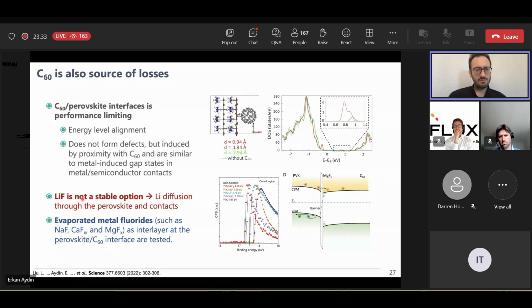in the past by lithium fluoride, but this is not a viable option for the long term because lithium fluoride is a bit tricky. Lithium is diffusing into the perovskite and other contacts, and in the end, we lose this layer, and plus it's also causing performance losses. So you can use any other metal fluoride as well, not necessarily magnesium fluoride, but in this example, we found magnesium fluoride works very nicely.